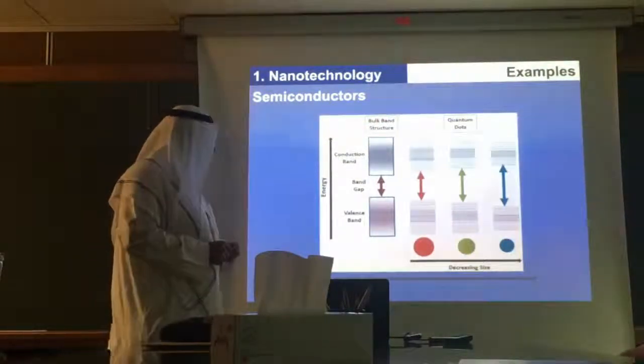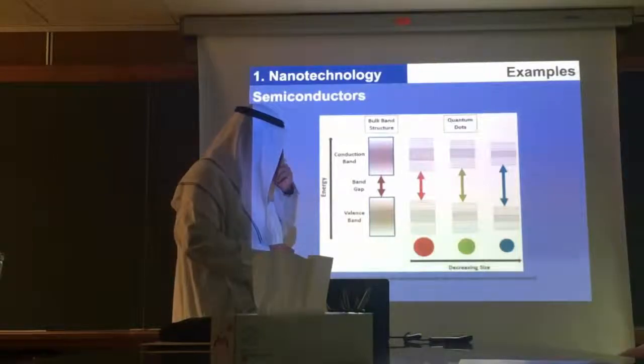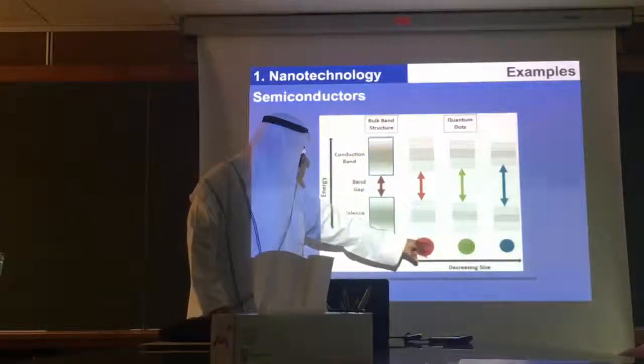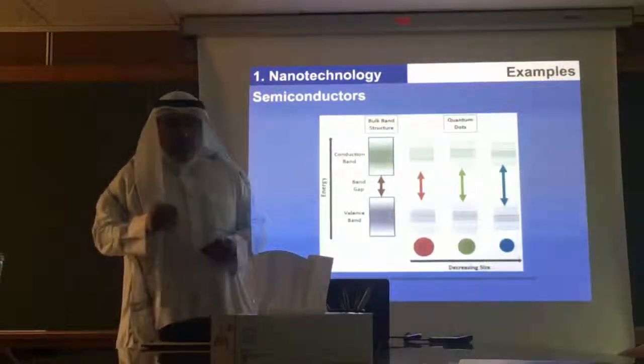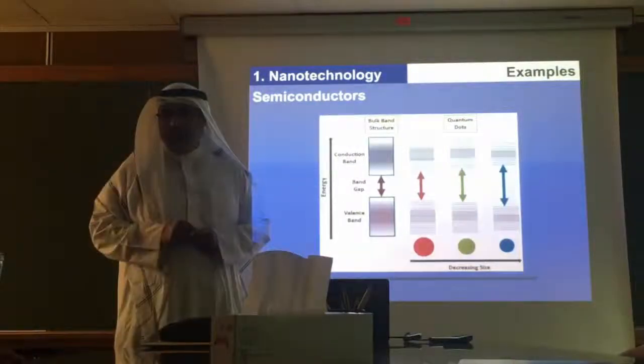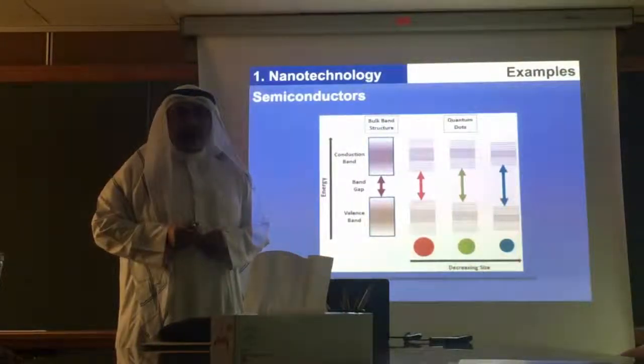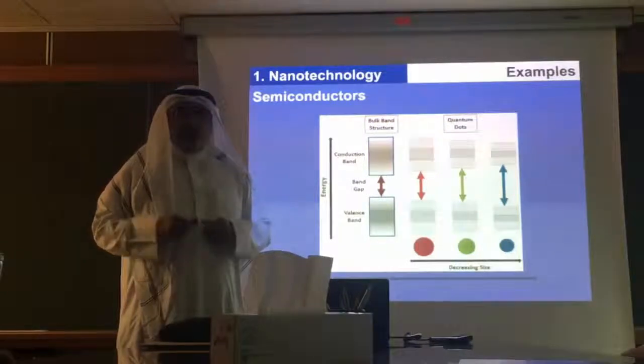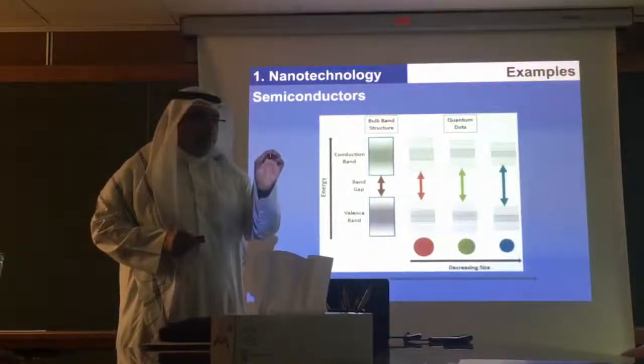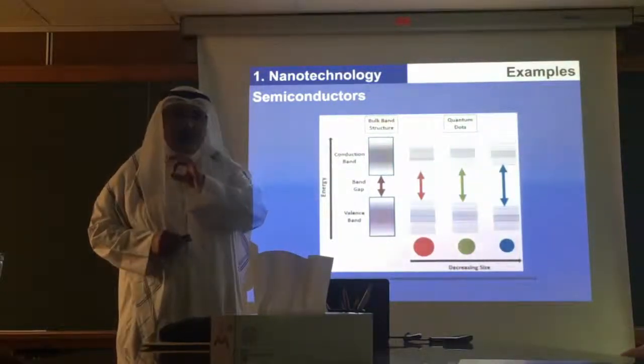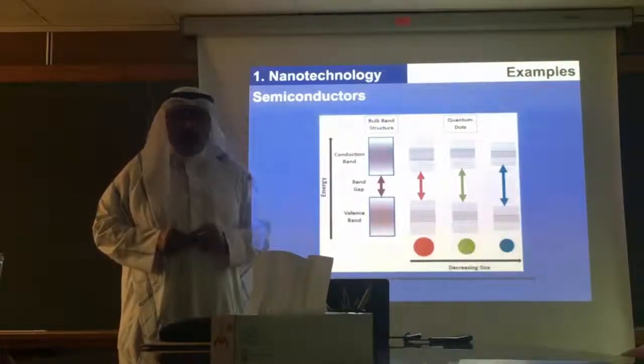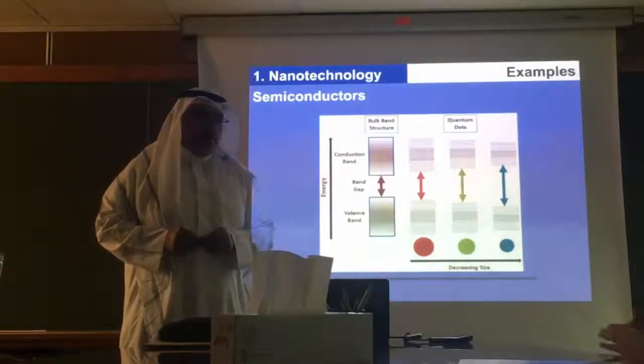And I did some work in this field a long time ago, and I used the titanium dioxide, and then I put on top of it gold nanoparticles. And I found out this enhanced very much the photocatalytic properties. And we found out by controlling the size of the gold nanoparticles, we get different control of the photocatalyst.